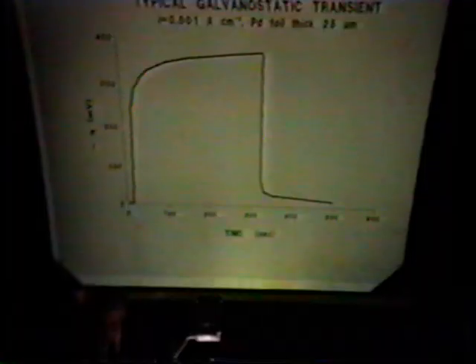And so the overpotential goes up and comes to a rise time, the constant part, which is a few hundred seconds, 100, 200. Well, now, that provides us with a problem in our mechanism first, because, you know, we've already said that it's going to be this discharge coupled, this discharge combination, because you can calculate what the rise time ought to be. It's a very simple calculation. It's just 4 times C times RT over F divided by the current density. And that formula, by the way, comes into all kinds of electrical engineering, too, apart from electrochemistry. Just consider a double layer condenser as discharging. And you then take, quite uncontroversially, 50 microfarads per square centimeter for the palladium surface, and we're talking about a milliamp, 10 to the minus 3 amps. It works out 4 times 10 to the minus 3 seconds.